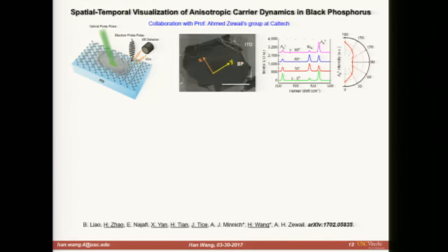One of the most unique features of carrier dynamics in black phosphorus is that it has very strong anisotropy. The carrier effective mass along the x direction of the crystal and the y direction differs by a factor of 10 - it's 10 times smaller along the x direction. So carriers move a lot faster along the x direction compared to the y direction.